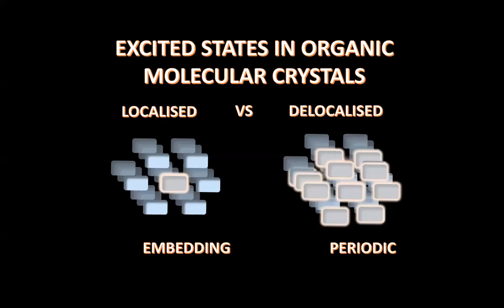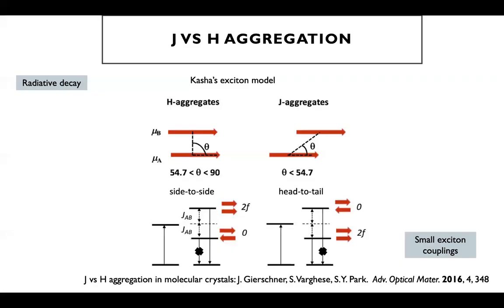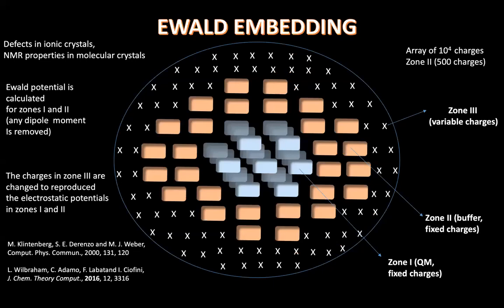And of course, we have the question, do we use localized or delocalized methods here? And for us, we've seen that the best choice is to use localized methods just because of the features that I described before, because the excitations are clearly localized. But in a way, we shouldn't forget that we have a crystal where we have long-range interactions with the periodic system. So this electrostatic interaction will still affect the photochemistry of the system. To deal with this situation, we've been using methods that are based on the Ewald embedding approach.